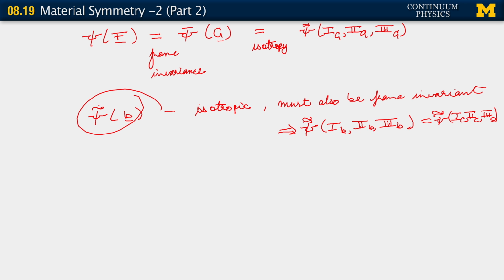This is a fundamentally unsound model for a fiber reinforced composite or a crystal. If you're trying to model a material that is a single crystal and you make it a function of B, dead wrong, can't work. Because you're then saying that your single crystal is isotropic, which is just not right. Same thing for a fiber reinforced composite. It cannot be a function only of B.